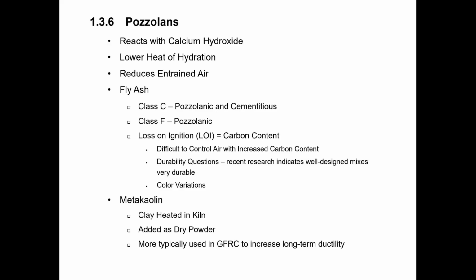Well, fly ash has a very interesting property in that it does react with a substance called calcium hydroxide. And when it reacts with calcium hydroxide, it does become cementitious. Well, it just so happens that when cement and water chemically react with each other, we get a byproduct from that reaction called calcium hydroxide. So calcium hydroxide is naturally occurring in our concrete because of the reaction between the cement and the water. Once the fly ash then comes in contact with the calcium hydroxide, it becomes cementitious.